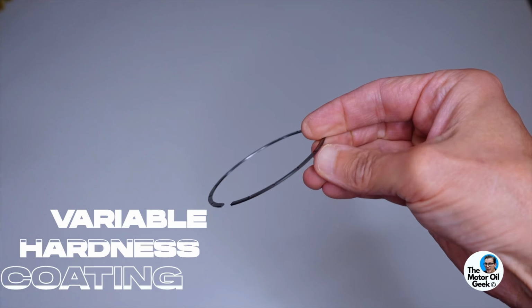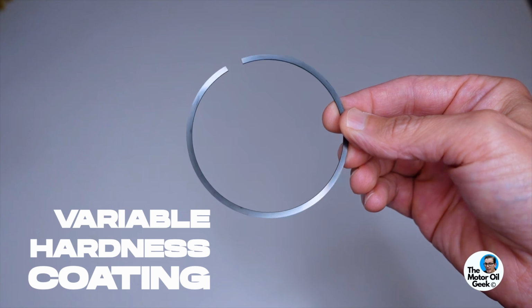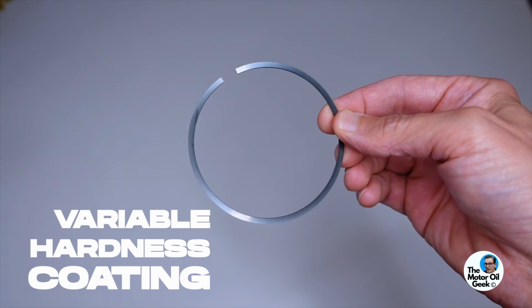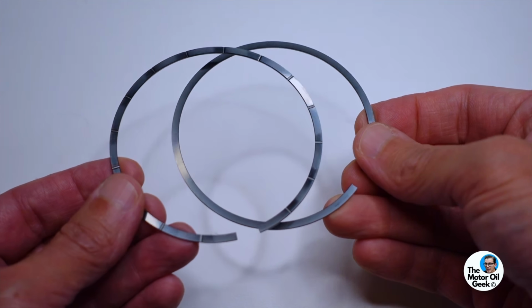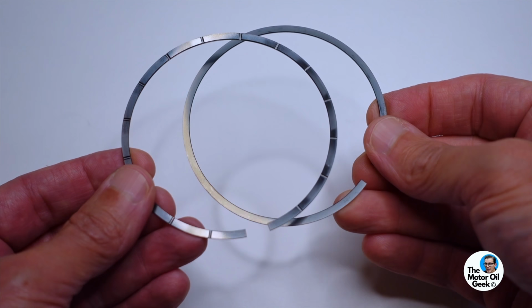So not all coatings are DLC. In fact, you guys here at Southwest Research have developed lots of different coatings. One of the most innovative ones is a variable hardness coating. Peter, explain what that is. Okay, so the hard coating itself, it's on a steel base, so in this case a piston ring, and it's a very hard coating. And as we go towards the end of the process, we change the constituents of the gas that are in the chamber, and that makes the coating become softer.